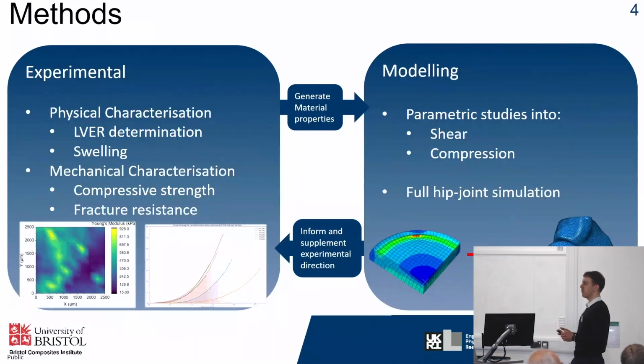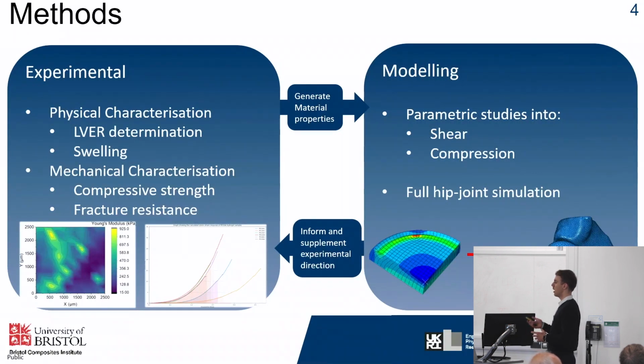The overall methods for my PhD fall into 2 main categories which feed into each other. So firstly, it's the experimental, which involves physical and mechanical characterization, such as determining the linear viscoelastic region. So this is key, as when the material is in a joint, it must always be operating within its linear viscoelastic region, so there's not irreversible damage to the material. The swelling characteristics are important within the body, and also mechanical characterizations such as compressive strength and fracture resistance, including